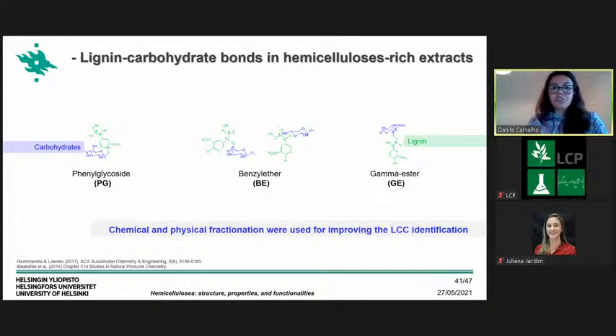And what we did for our samples was to check if their presence could be identified. And more than that, sometimes even if present, the frequency of these LCC bonds can be very low. And this can compromise the analysis, because since the polysaccharides and the lignin can be present in much higher frequency, it can be difficult to identify this single bond. So in our case, we also tried to apply some chemical and physical fractionation in order to concentrate the LCC bonds and also improve the identification of such linkages.